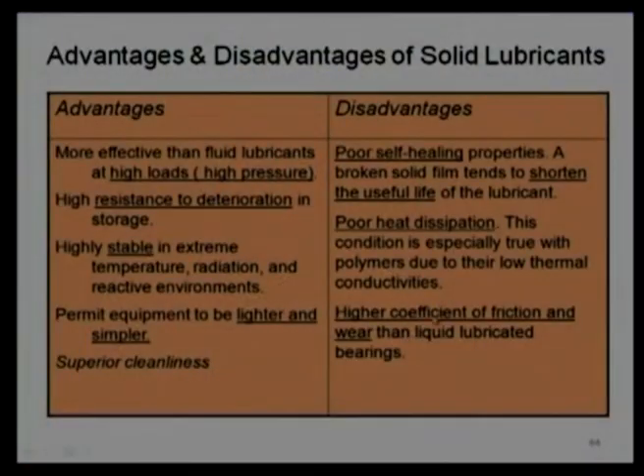availability of cooling agents or cooling devices, then we should not recommend it, the reason being that solid lubricants already show a high coefficient of friction compared to liquid lubricants. So, heat generation will be more at the solid lubricant interface compared to a liquid interface. In addition, if there is no provision to carry away the heat, and the applied load is very high and relative speed is very high, then we should not recommend a solid lubricant. The last disadvantage mentioned here is a high coefficient of friction and high wear rate.